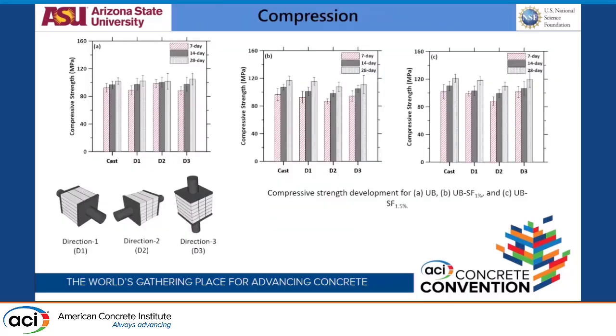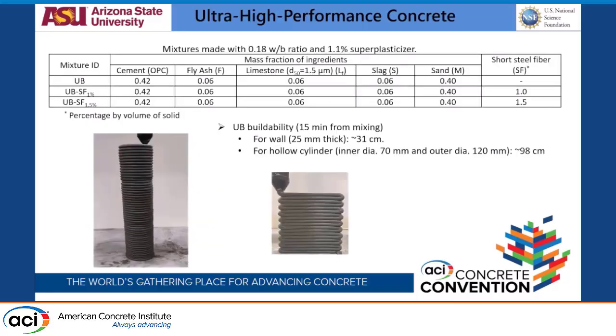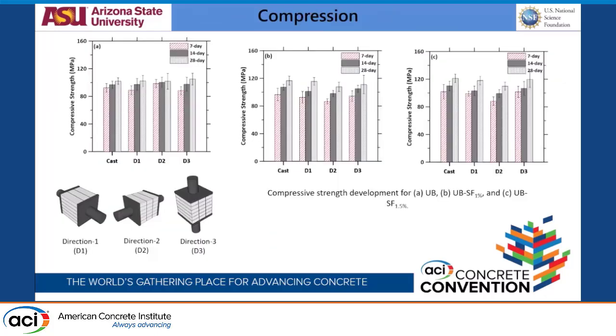For compression tests, we created large slabs from which we cut cubes, and we tested all three directions. We made a representative cast sample as well as a print sample. Shown in the figure from left to right are the UB, UBSF 1% and UBSF 1.5% mixes, based on the fiber volume percentage. On the left is the UB, and it goes to 1% and 1.5% on the right.